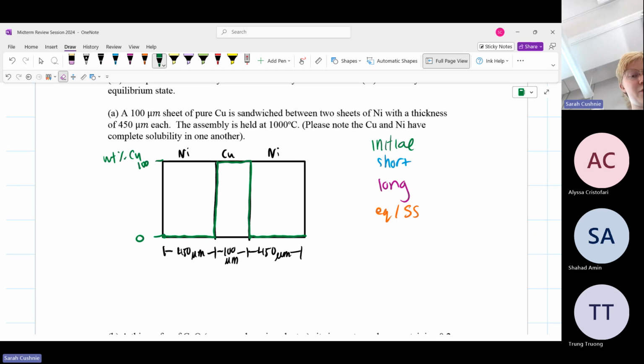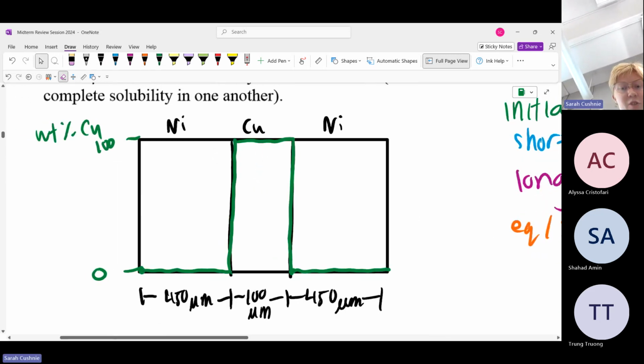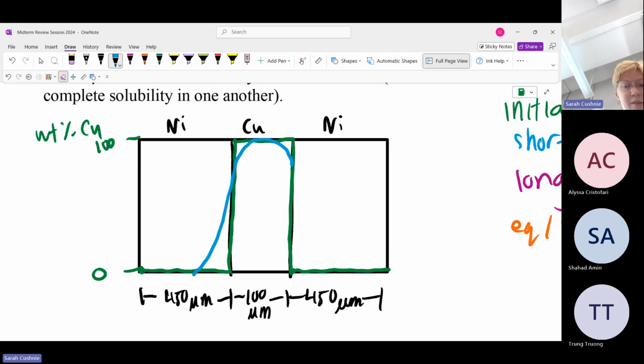And now when we start to think about short term, what's going to happen? We have less copper than we have nickel. So we can think about the copper starting to diffuse into the nickel, right? We have a little bit of this copper, and it's going to start moving in either direction, diffusing into the nickel. So instead of having this high concentration in the middle, it's going to start to go down because we're losing copper, and we're giving it to the nickel instead.